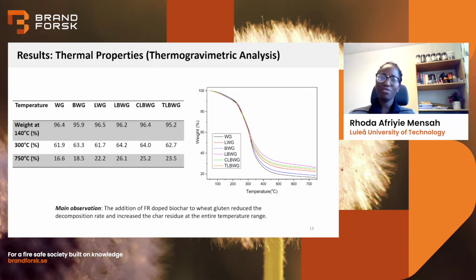If we look at the graph, we see that at lower temperatures, between 40 degrees Celsius up to about 200 degrees Celsius, the samples had a similar mass loss trend. And even on the table at 140 degrees Celsius, we see that almost all the samples lost about 5% mass. The main decomposition occurred between 250 degrees Celsius and 350 degrees Celsius.